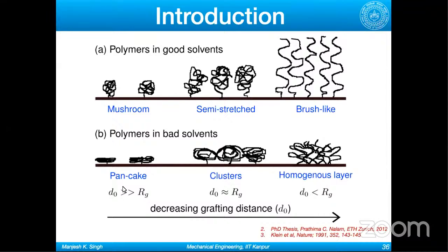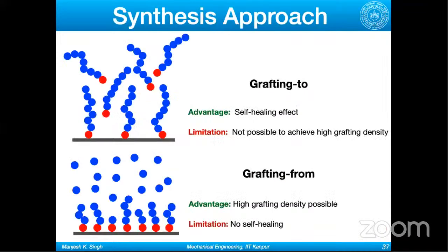If you repeat the same sequence in a poor solvent, when you are far apart, you will form a pancake-like structure. If you bring them closer, they will form a kind of cluster. And if you bring them even closer, they'll form a homogeneous layer on the surface. They will not stretch out in a poor solvent, or bad solvent, I mean bad means poor solvent, to form a brush-like structure.